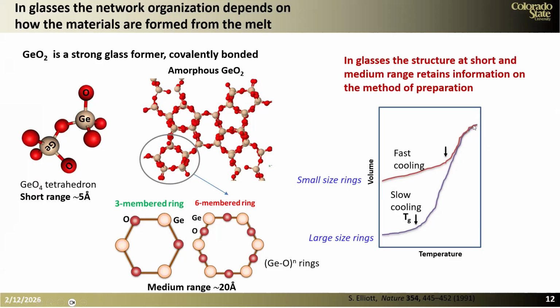But notice that if I go much slower, now I will be able to get a very different configuration in the amorphous material than I do when I cool very fast. And typically, I show you the example of amorphous germania at the atomic level, and in what we call the short range, in the range of about 5 angstrom. In germania, the germanium atom is coordinated or is connected to 4 oxygen atoms, and these are how essentially the molecules connect.